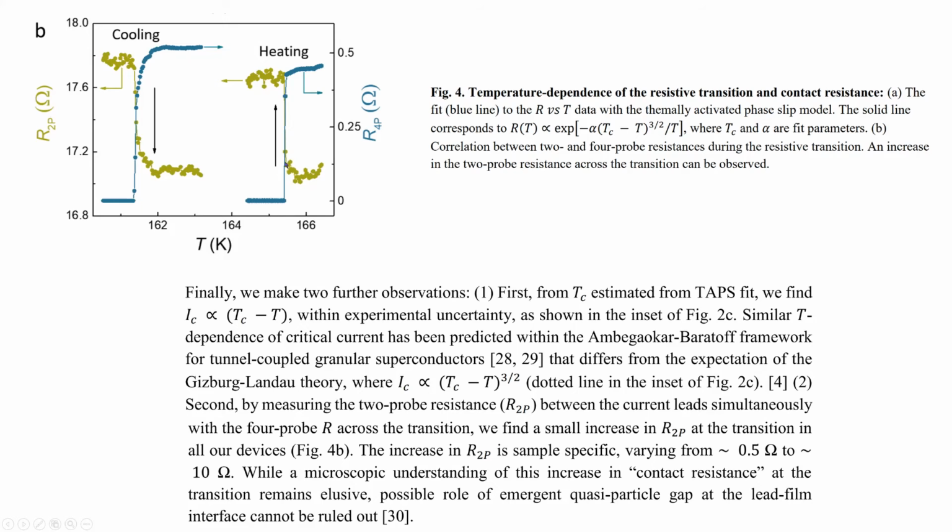That when you're heating, and let's say you're increasing the temperature, suddenly as soon as the resistance becomes finite, or whatever it is, 0.5 ohms, there's a sudden drop in the 2-terminal resistance. So this is really unusual behavior, especially if one were to interpret this as the onset of superconductivity that is being controlled by temperature parameter. First of all, it's extremely sharp,